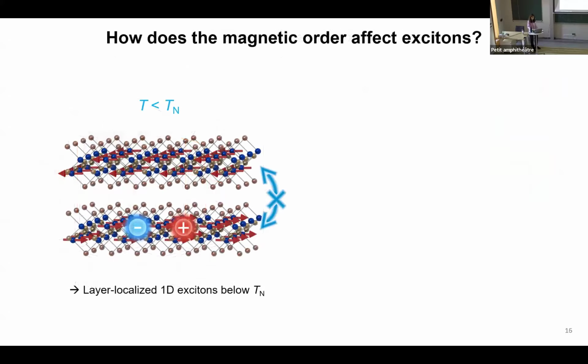So, good. Now that we have understood that we have degeneracy lifting due to the anisotropic dielectric function in chromium sulfide bromide, it is interesting to see how this internal structure changes with the magnetic environment surrounding these spins. So, when we did our measurements in the antiferromagnetic state, what is special in the antiferromagnetic state is that the electron and hole pairs, once generated, are strongly bound to only one layer here. Why? Because the electrons or holes cannot hop between the layers. Interlayer hopping would require flipping the spin. This costs energy, so the interlayer hopping is spin forbidden.